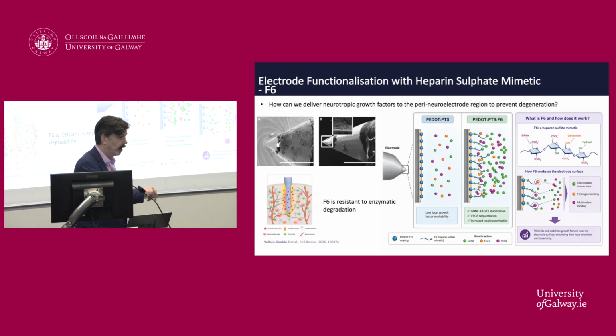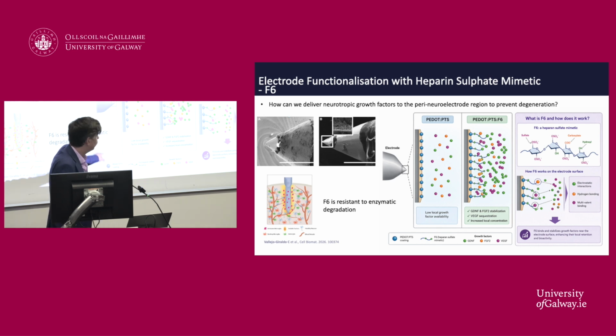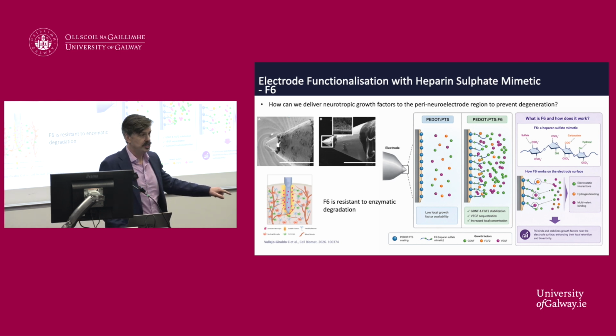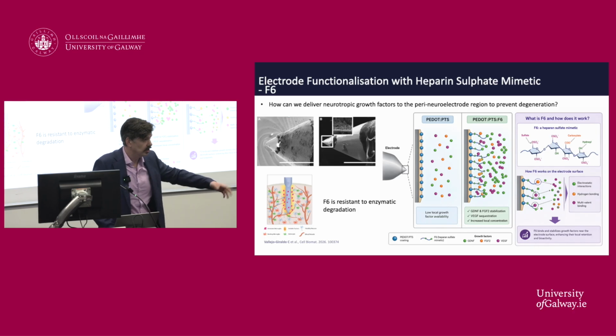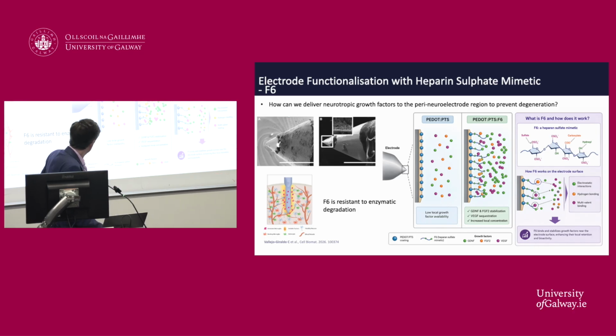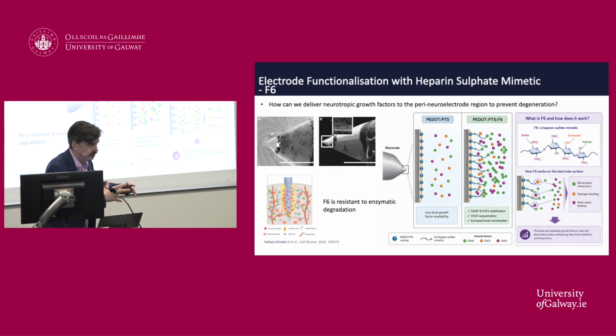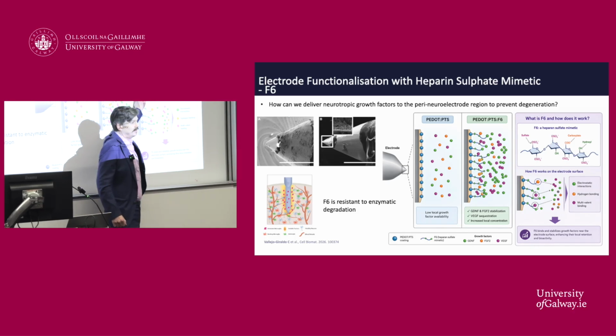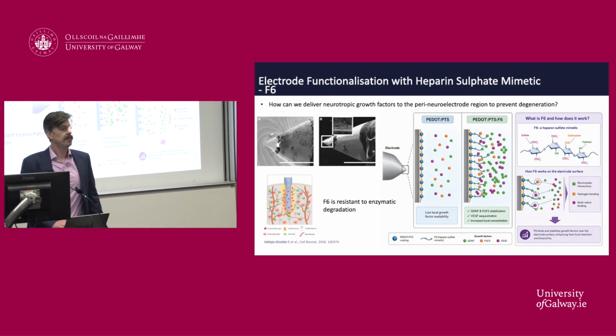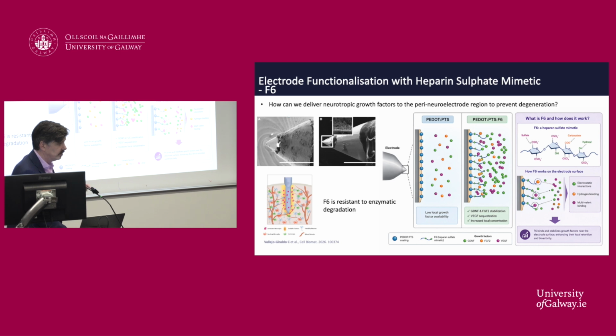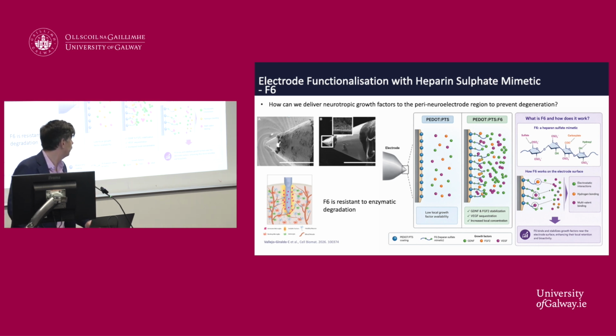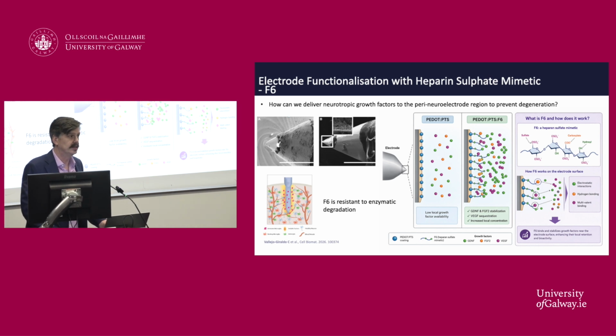We didn't use heparin sulfate. Why? Heparin sulfate itself is very unstable. It undergoes enzymatic degradation or decay quite rapidly endogenously. It also doesn't bind to very many growth factors. So what we wanted to do is to make that heparin sulfate mimetic stable and to make it have high affinity for growth factors. So we engineered it. We called it F6. F6 is a heparin sulfate mimetic that's resistant to enzymatic degradation, and it also contains lots of sulfate groups, and these sulfate groups are important for binding of growth factors.